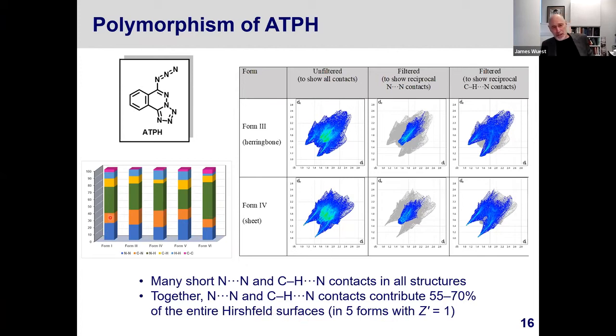At least this is only 5 of the 7 forms. We left out form 2 because it's a low temperature form related to form 1, and we left out form 7 because it has Z prime equals 4. So we limited the cases, but basically in all the structures, this generalization is true, that these NN and CHN interactions are legion. Also, by comparing form 3, which is herringbone, and form 4, which is a sheet structure, you can see here that the Hirschfeld surfaces, either filtered or unfiltered, are very closely similar. So again, this molecule can do all sorts of stuff without really changing the ultimate story.